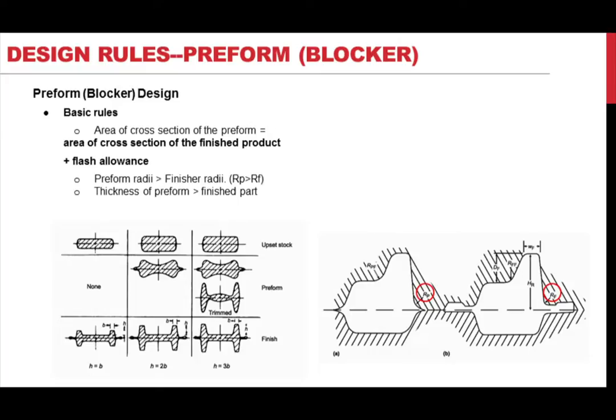One of the most important processes in die design is designing the preform or blockers, which is an especially difficult task, requiring skills that can only be achieved by years of extensive experience. The basic rules for preform design are: first, be aware that the cross-section area of the preform equals the sum of the cross-section area of the finished part and the flash allowance. Second, the preform radii should be greater than the finisher radii in the same position. And third, the thickness of the preform should be greater than the finished part, so that the metal flow is mostly by upsetting rather than lateral extrusion.